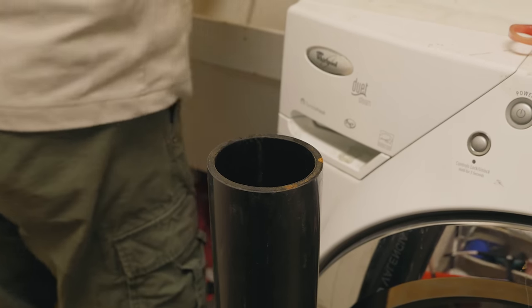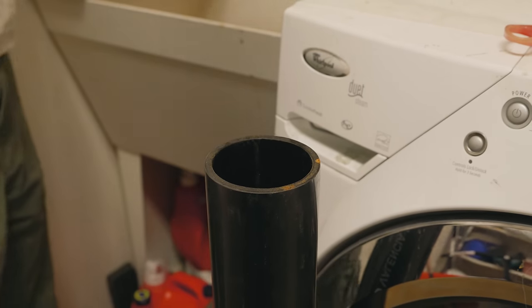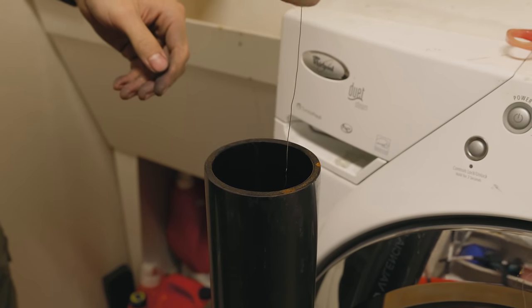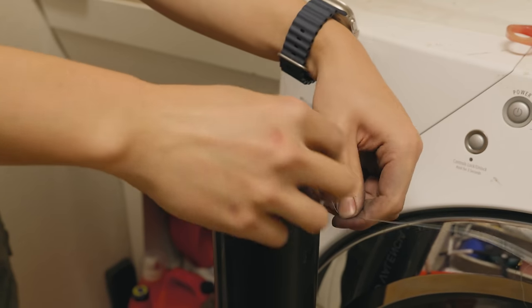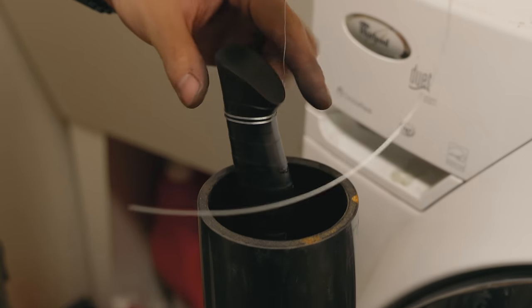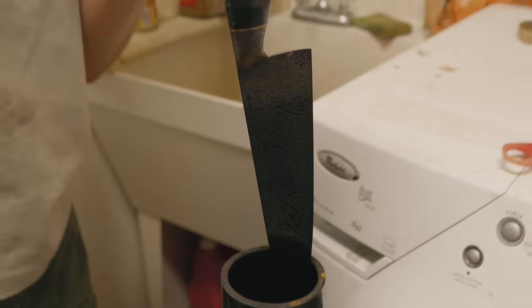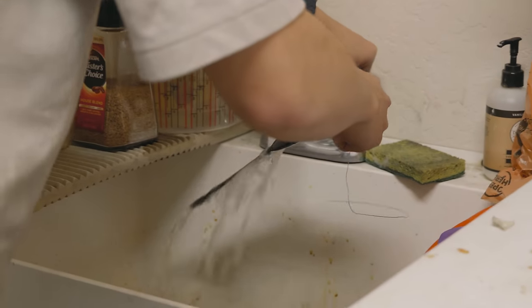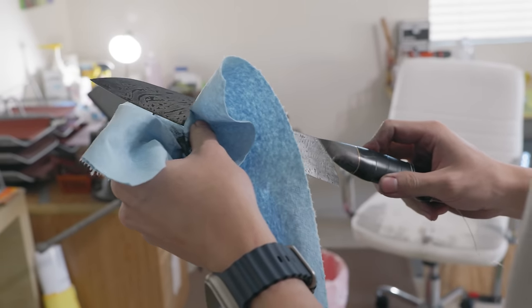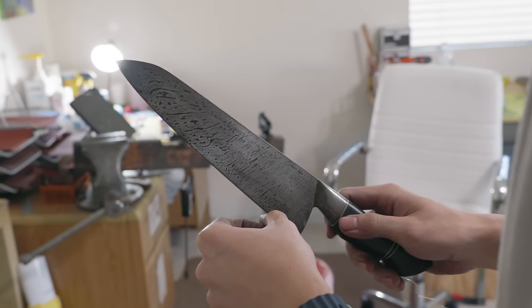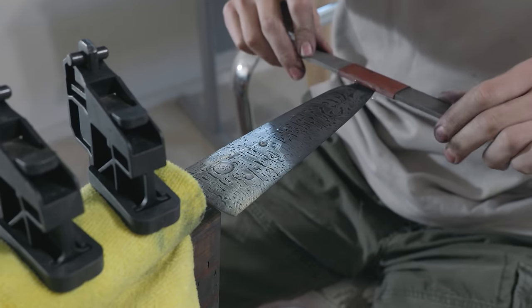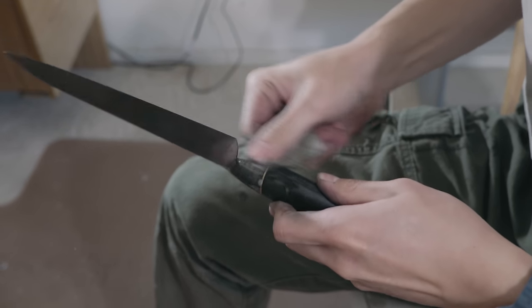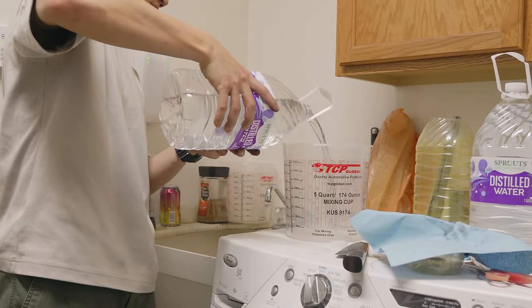After cleaning everything up with 2,500 grit sandpaper and cleaning the transitions up with a 5,000 grit sanding pad, it was time to go in for etch cycle number two. In terms of what's different between the first and second etching cycle, the only difference is that the second one comes after the first one. One of the side effects of etching with ferric is that it actually etches depth into the material, and sometimes if the edge is too thin, you can actually etch like these little serrations into your edge, and that's not something I wanted. I was using the edge of my fingernail and running it along the edge of the blade to make sure that the edge was still flat, and luckily it was.